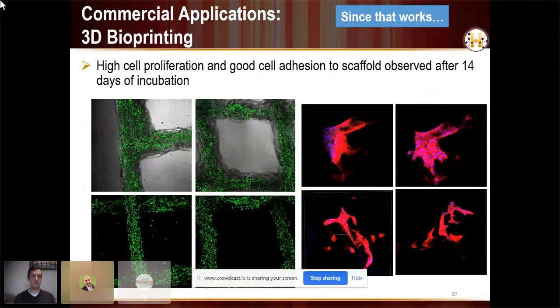So you can see every green dot in the image on the left is a cell. We can print at extremely high cell densities and with quite good resolution on the printed features. And we get a lot of actin staining in the images on the right, indicating that cells are adhering well to this platform. And this is actually with one of our 3D printed platforms. So again, we're looking to see how far we can push this, what structures we can get, what resolution we can get, and what applications we can ultimately do, to hopefully engage partners in this as well.